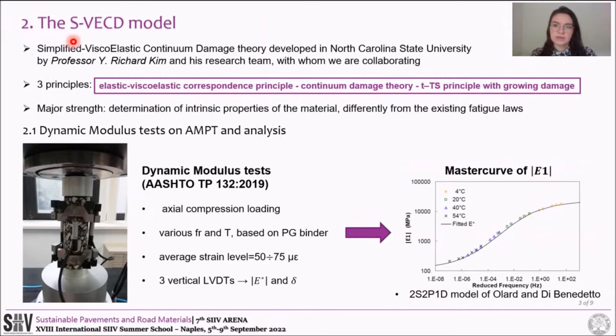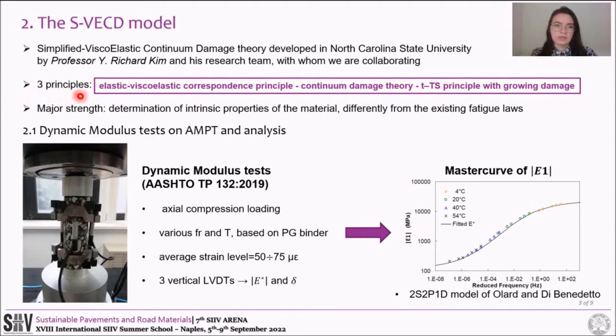The Simplified-ViscoElastic Continuum Damage (S-VECD) theory for the investigation of fatigue performance of asphalt mixes was developed by Professor Richard Kim of North Carolina State University, with whom our research group has collaborated for several years. The theory is based on three fundamental principles: the elastic-viscoelastic correspondence principle, the continuum damage theory, and the time-temperature superposition principle with growing damage. The major strength of the S-VECD model with respect to existing fatigue laws is that intrinsic properties of the materials are determined.